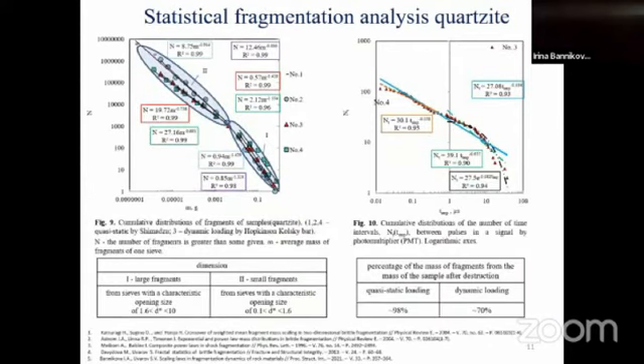This slide shows the cumulative fragment distribution for quartzite samples obtained under quasi-static and dynamic loading. The curves have two slopes. Each is described by a power law, which is typical for the distribution of brittle materials. For large fragments, the power in the law was the same for all samples. For small fragments, the exponents were different. Part of the curve runs below. This is possibly related to the formation of fragments as a result of the breaking of large fragments.